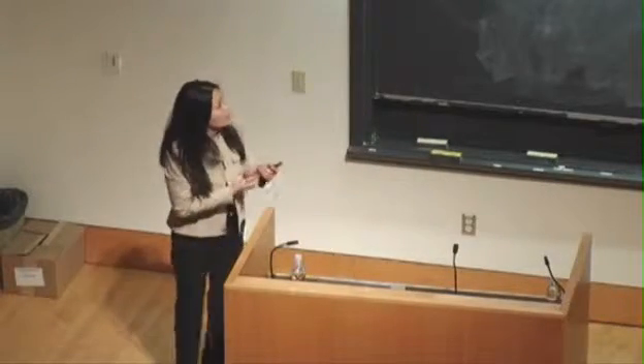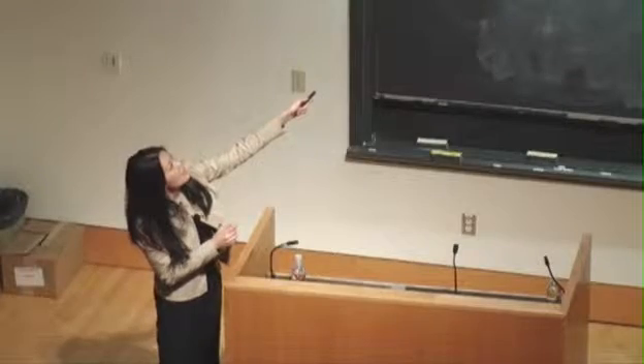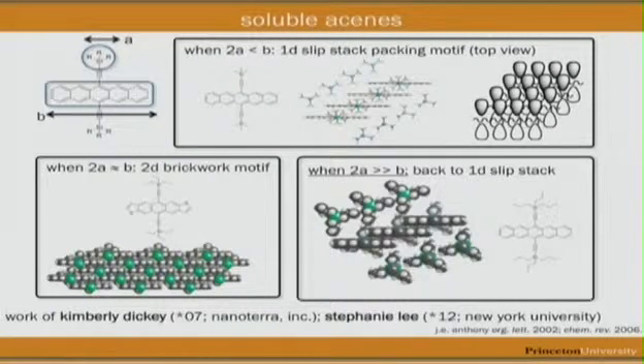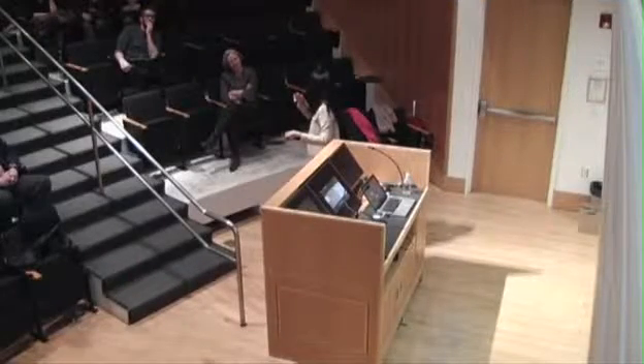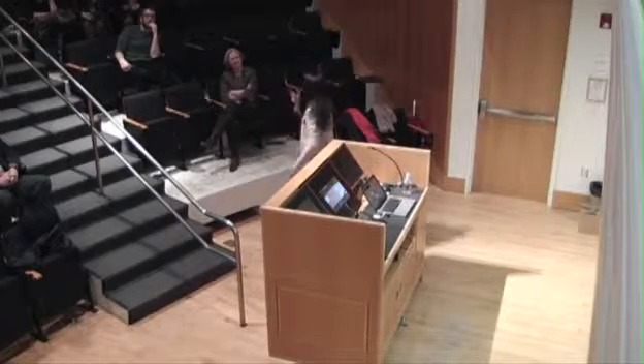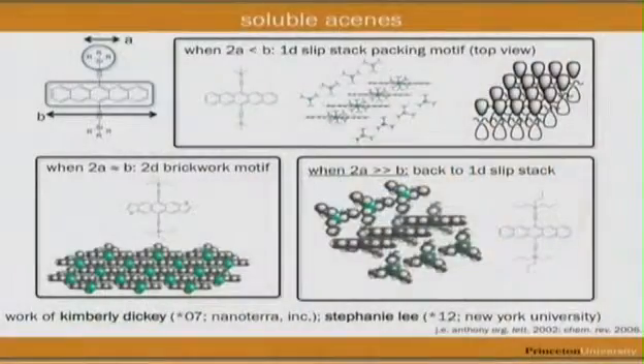So if you look at the chemical structure of this guy, there's one sulfur on this side and one sulfur on the other side. When the sulfur is on the same side, that's scrambled. And so when we get a macroscopic sample from them, we've got two isomers. So we get those two isomers, and you can't easily isolate them. And so that creates inherent disorder within even a single spherulite. So the low mobility is basically dominated by these kinds of local disorder that we can't get rid of.